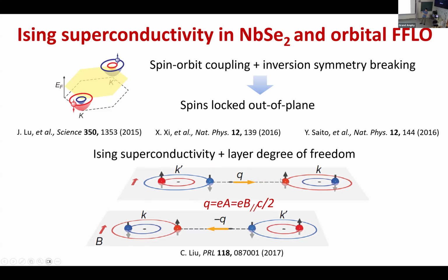So that means within each plane, you still have zero momentum, but relative to each other, the upper layer and the bottom layer have a shift in momentum space. So this is also finite momentum. There is a finite momentum in there. Because of this finite momentum, people also call this FFLO state. But the origin of this is not Zeeman splitting anymore, so this is why they call this orbital FFLO state.